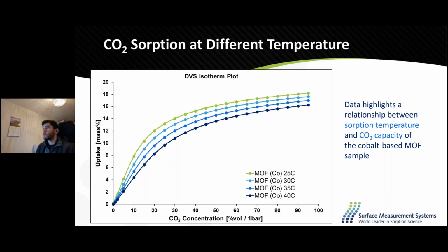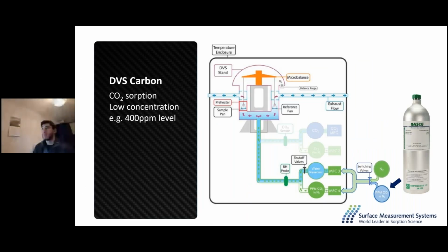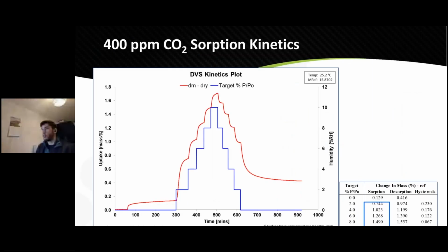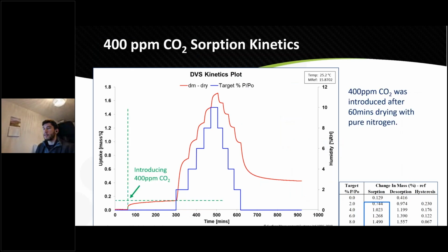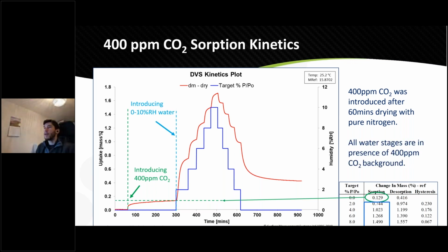And a couple of examples with low concentrations of CO2, so ppm level, in this case 400 ppm. And this is where we have 400 ppm plus water on top. So we see here that the sample is exposed to 400 ppm. There is an adsorption, and then what's happened is water is introduced on top of CO2. So again, co-adsorption of CO2 at low concentrations and water. That's where the water is being introduced.